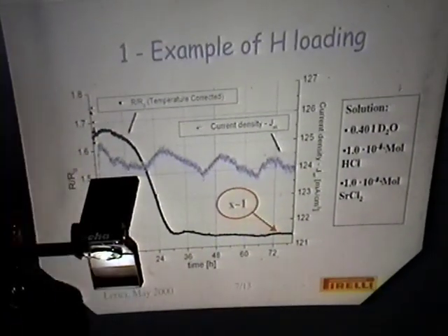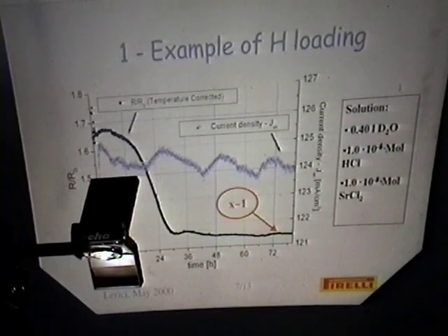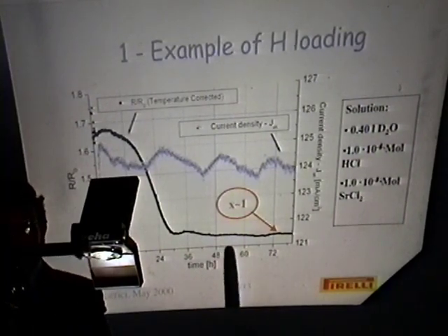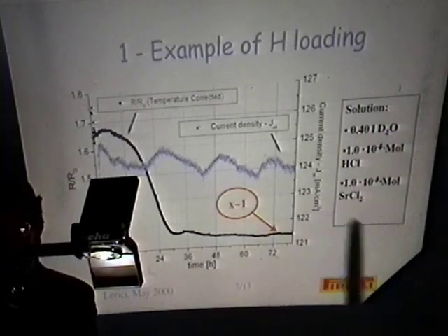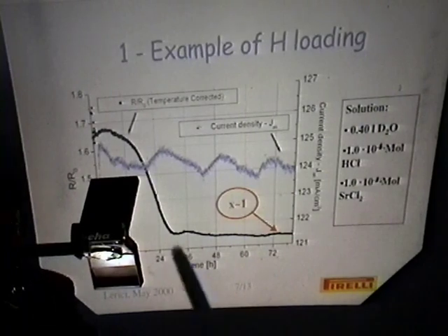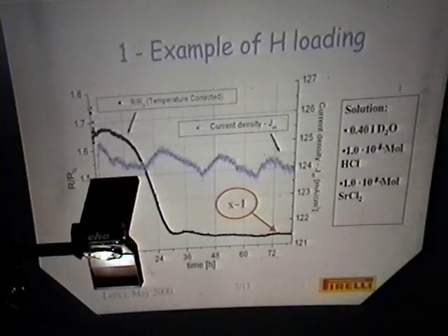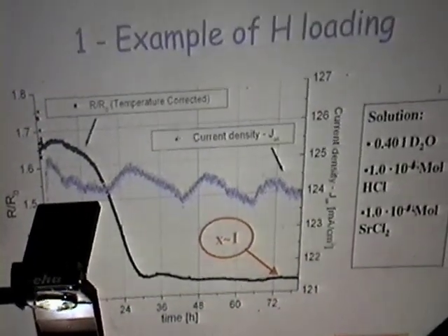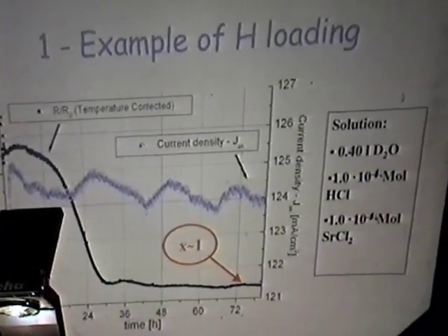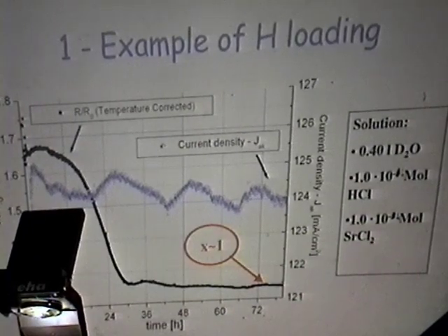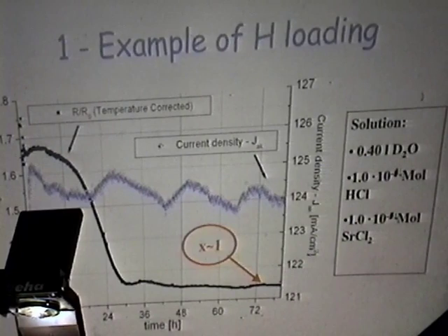I want to show you an example of hydrogen loading in a thin palladium wire. You can see here the time in hours, the relative resistance in black, and the current density in blue. The value of the resistance is corrected by the temperature, but this correction is small. I mean that in our cells, the temperature could vary by about 1 to 5 degrees Celsius. So there could be a small correction on the real relative resistance value of about 0.01 or 0.02.